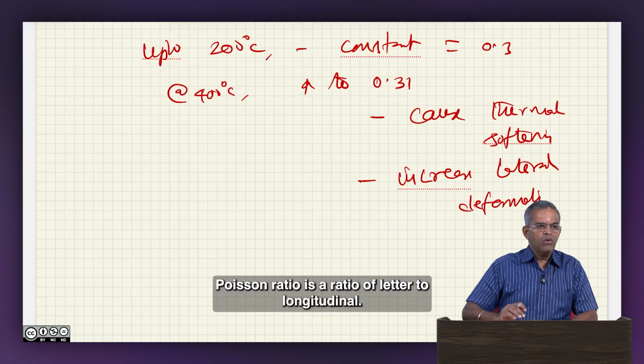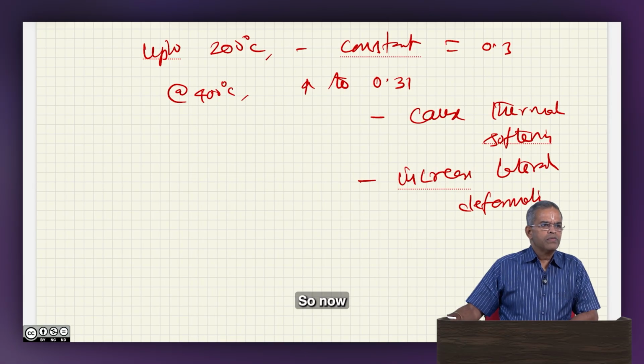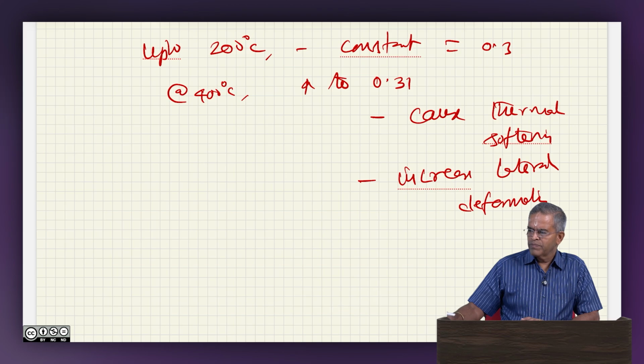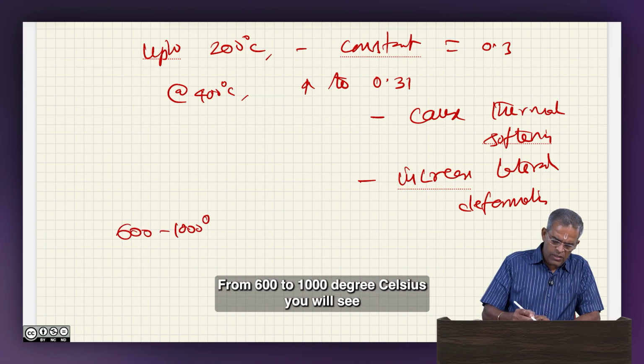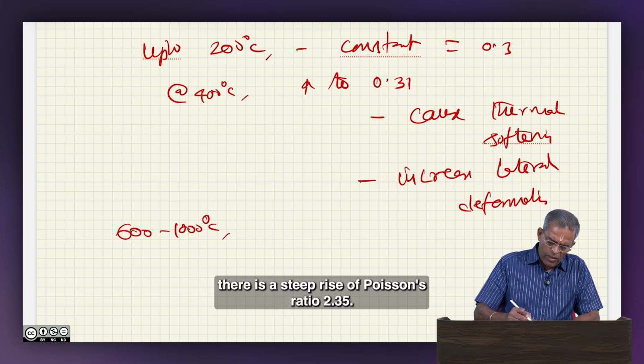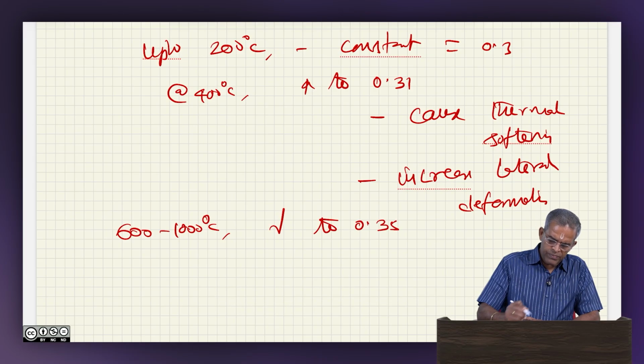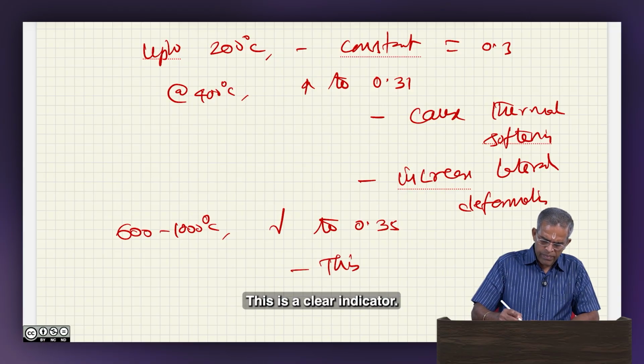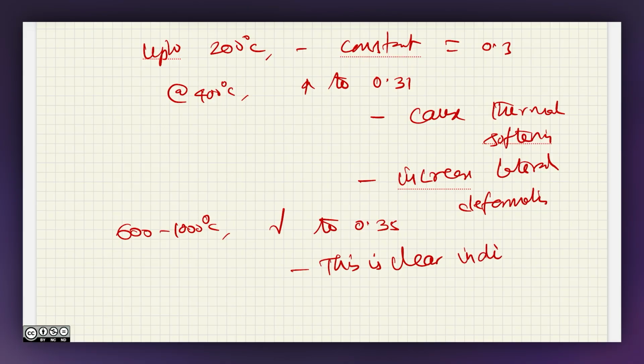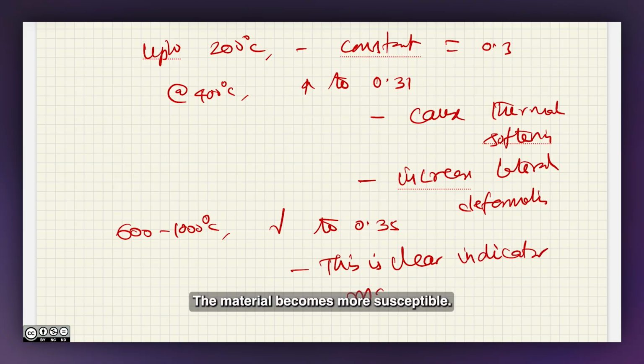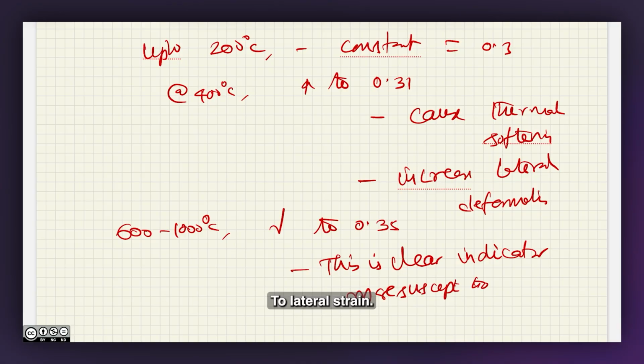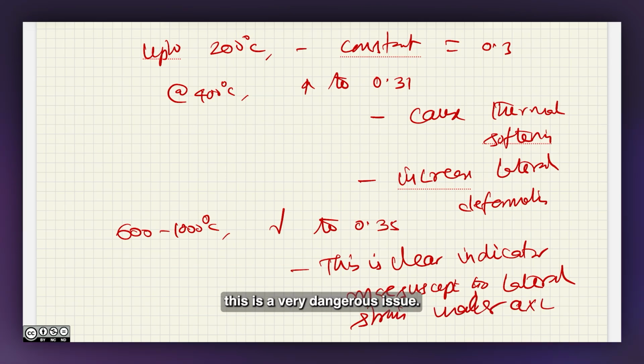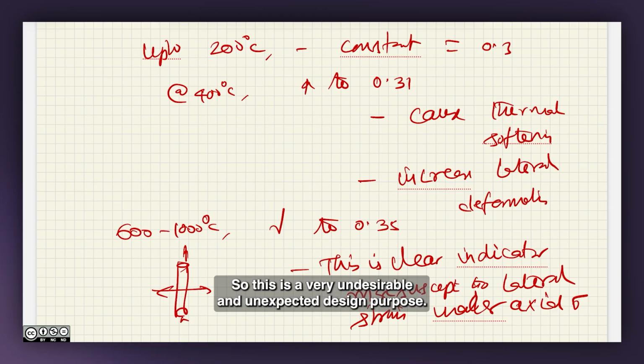Poisson's ratio is a ratio of lateral to longitudinal strain, we know that. So, now from 600 to 1000 degrees Celsius, you will see there is a steep rise of Poisson's ratio to 0.35. This is a clear indicator the material becomes more susceptible to lateral strain under axial stress. This is a very dangerous issue. So, you apply axial stress, okay, but the lateral strain is increasing.